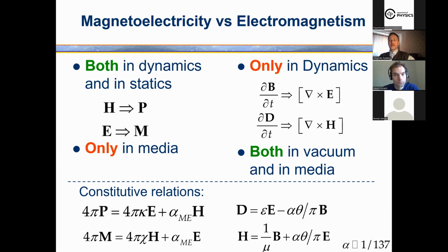It's a kind of generalization of the case of magnetoelectricity, because in the case of multiferroics and magnetoelectrics, usually these coefficients are constant. But in the case of axion electrodynamics, it's a kind of field theta. So it can also be a dynamical one, and maybe inhomogeneous, and so on.